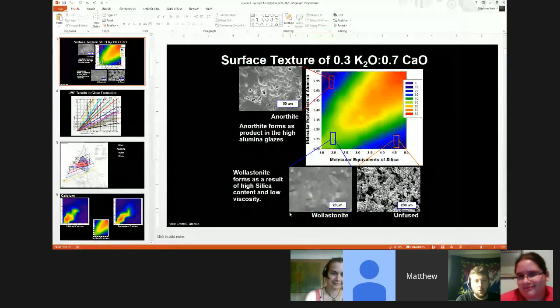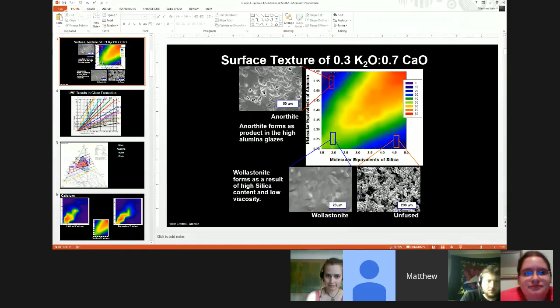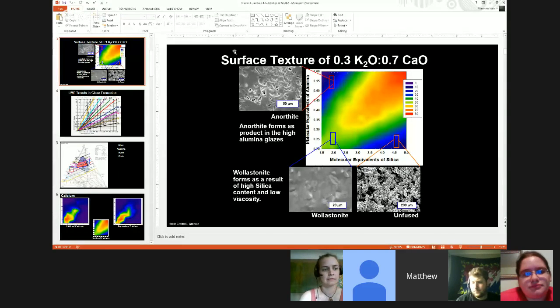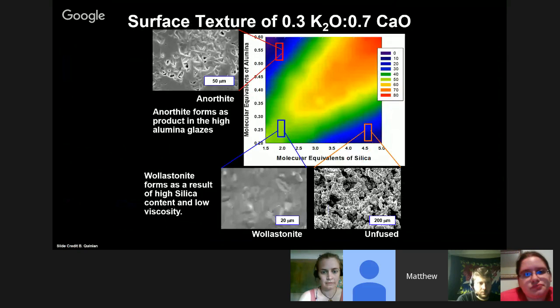So going back to calcium precipitation. Everybody sees the SEM images? What we have in the upper left-hand corner is anorthite, and in the lower corner we have wollastonite. We know from reviewing our materials that the composition of wollastonite is one calcium and one silica.